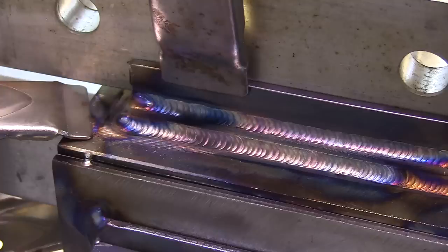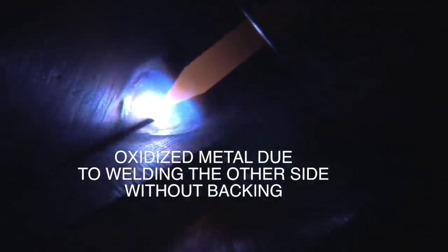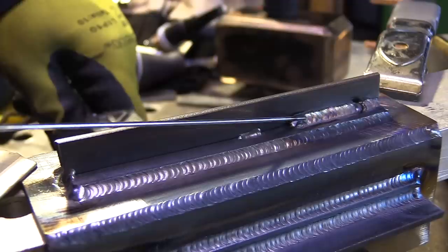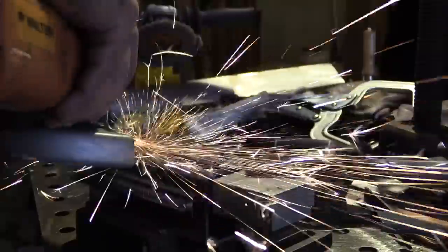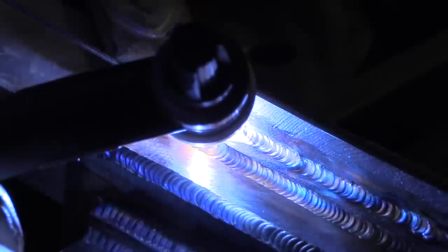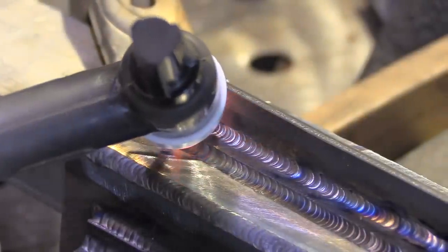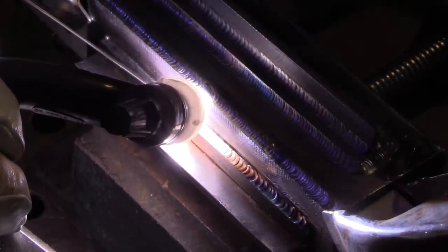So we're going to talk now about what happens when you have to weld the back side of an area that you've already welded the other side of. You want the puddle to flow like this, but when you weld one side and then you go to weld the second side, it usually welds like this. That's horrible. All that oxidation, all that scaling, you just really can't even define the puddle hardly. And so what I'm going to do here is I'm going to take a slitting wheel and just shave it. Just try to shave the oxide film off of there and see if it'll weld better by doing that. I'm putting very light pressure here. I don't want to put big grinding marks in here, but just laying the slitting wheel on its edge. It cleans it up quite a bit. It's not perfect, but it's going a lot better than it was prior to cleaning it up. It goes a lot better if you just put aluminum backing on the back side. It pulls out enough heat and traps a little argon in there where it welds almost as good as the front side.